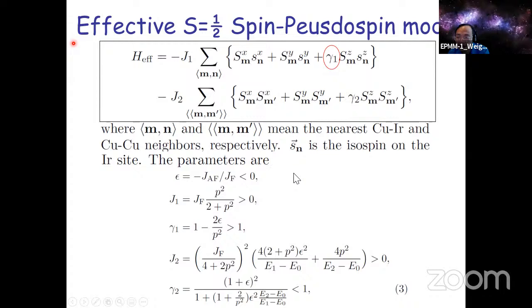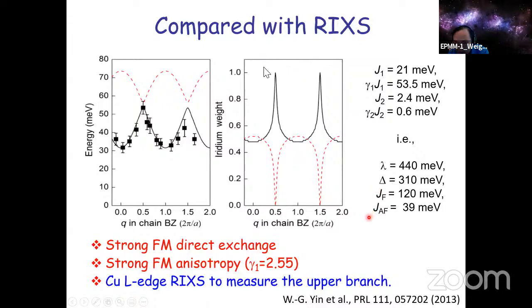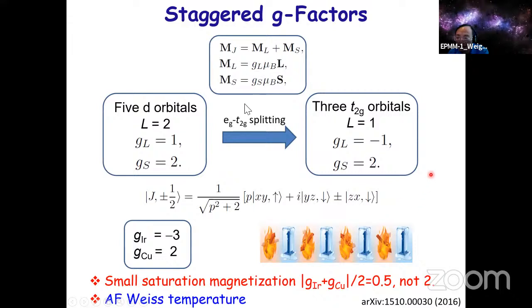So if we project out the lower lying total angular momentum 3/2 states, we get the effective spin half on the copper side, and the pseudo spin half on the iridium side. And this gamma 2 is the anisotropy parameter. So we can solve the Hamiltonian, and we can get the spin excitation spectrum and compare with the experiment. We find that this number is 2.6, so it's quite strong. Then we also calculated the Lande g factors for this material. What's interesting is that we get the iridium g factor is negative, it's -3. And the copper, that's a real spin one, so it's 2. So we have a staggered g factor. This staggered g factor is why we get a small saturation magnetization.